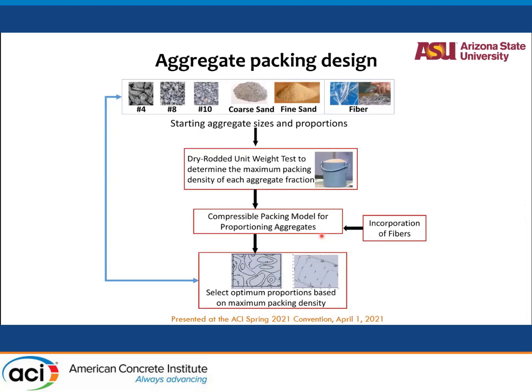Now we will go to the aggregate design. And aggregate design also was based on a packing model. We had aggregates all the way from number 4, which is passing or retained on 4.75 mm sieve, so maximum nominal size of 4.75 mm. And all these different aggregates, 2 types of sand, a coarse sand and a fine sand, and we use steel fibers. We use polymer fibers also, but I'm talking about steel fibers in this work.